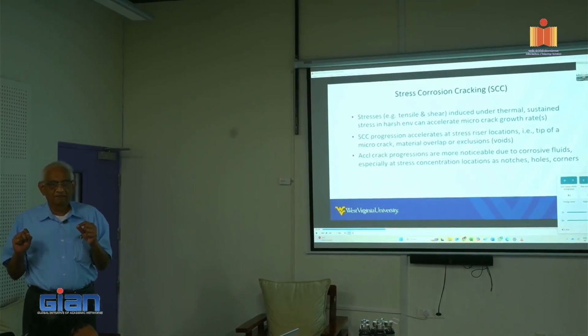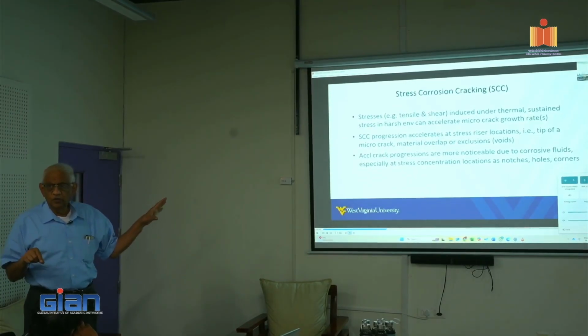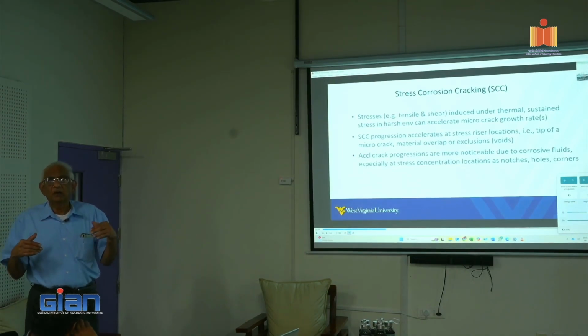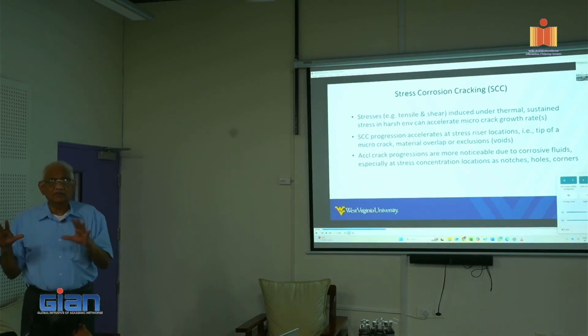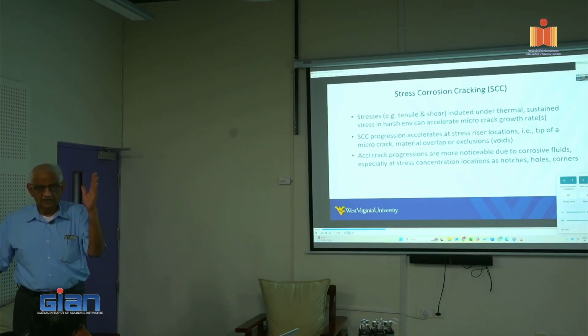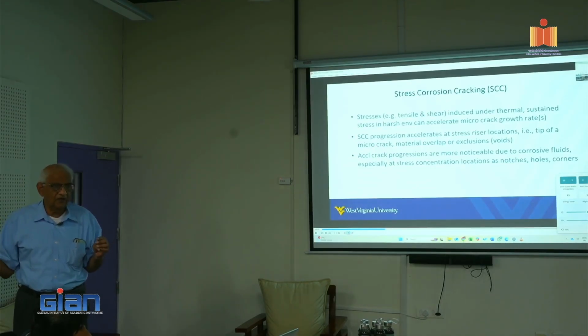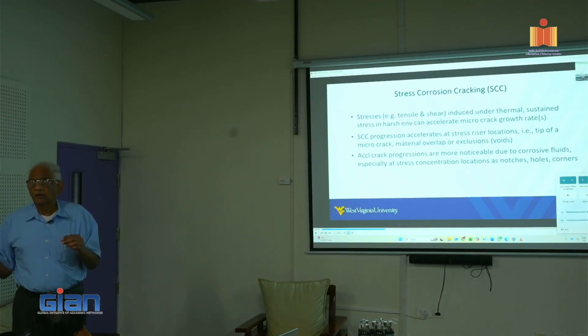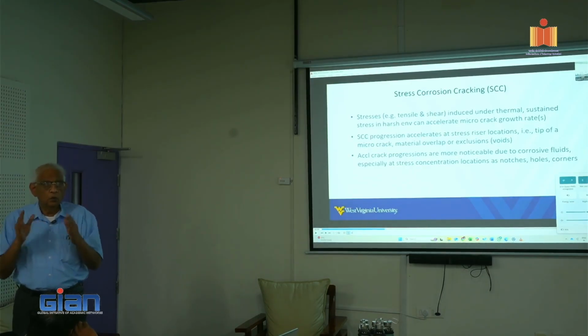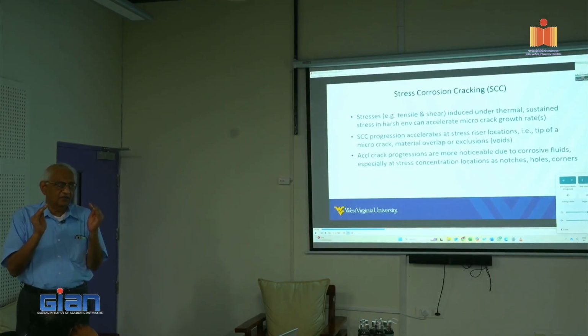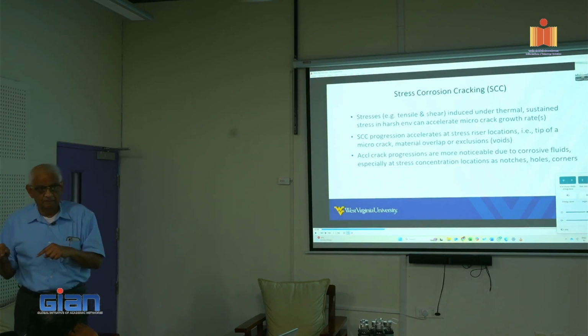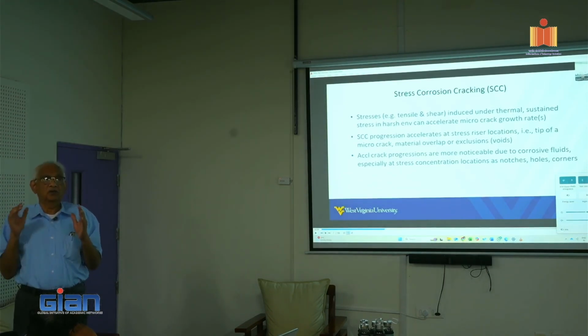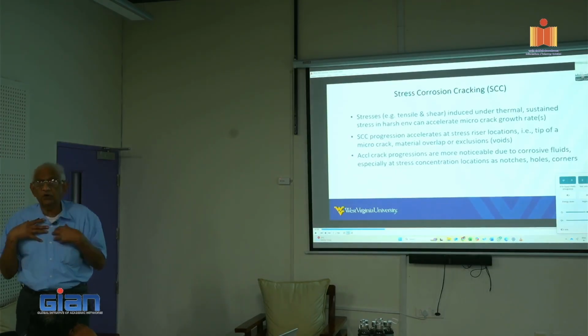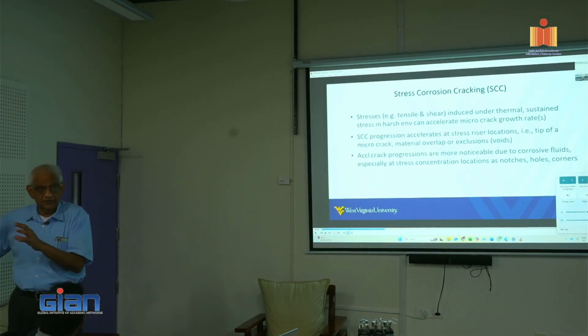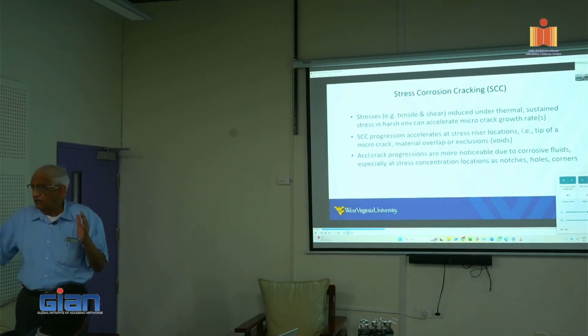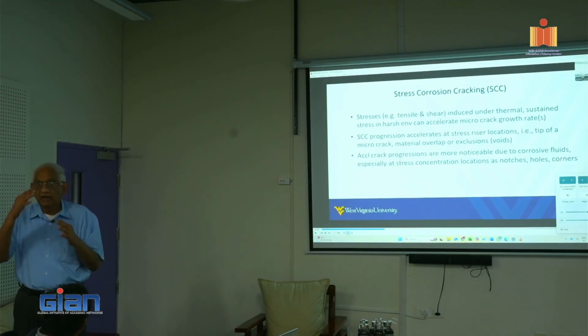We must have, so this is going to be, I don't know whether I had shown the actual Arrhenius procedure in my thing or not, but this is a semi-log scale, with the strength on the vertical and the aging, the number of hours or number of years, on the horizontal scale. That is the aging scale. So what we do, we need to get some rate of degradation coming out from the naturally aged material. Without that I cannot. But what I can do, however, is if I get a 2-year, 3-year, 5-year data, which is what we did, and I establish the trend, then I make a correlation from this 2, 3, 4, 5-year data, then I extrapolate it to 100-year data. So that is, I have to curve fit.